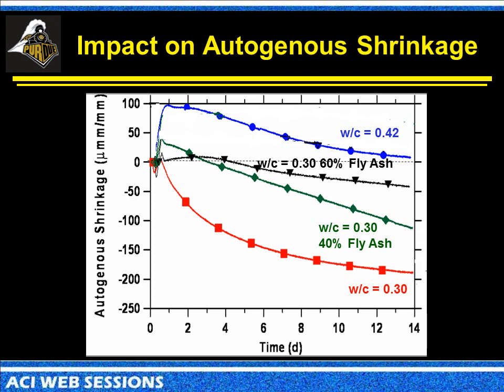And when we stop and think about this, this kind of makes sense because we've got more reaction going on early with our plain Portland cement system. Our fly ash system is reacting a little slower, but we're getting that autogenous shrinkage taking place. In addition, the thing that's important to remember is our fly ash system is going to have more chemical reaction shrinkage taking place in the system. So more chemical shrinkage, about double what we see in a normal Portland cement system, which is going to drive an increased autogenous shrinkage in these mixes.